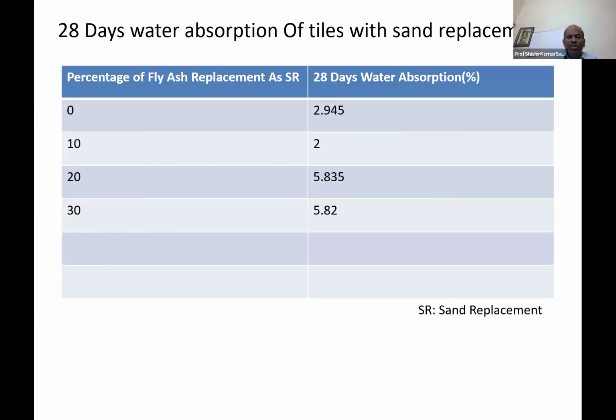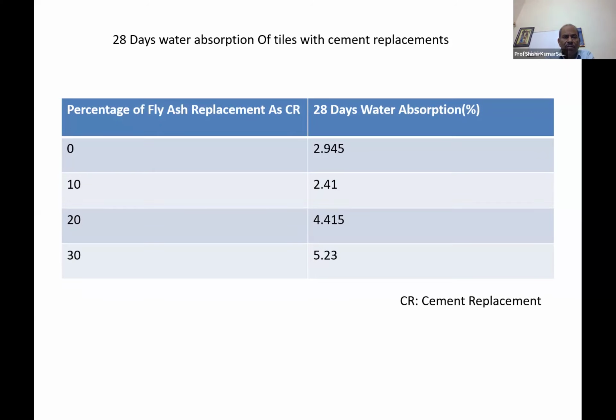So this is water absorption, 20%, 30%. I think the maximum water absorption is 4% or 6%. If it is 4%, we can limit ourselves to 10%, but it has to be checked. I forgot whether it is 6%. If it is 6%, then we can go up to 30%. 28 days water absorption of tiles with cement replacement, against percentage of fly ash replacement. So it goes on increasing, highest with 30%, and 5.23 at 30%, which is much more than 0% replacement. So it can easily be used.